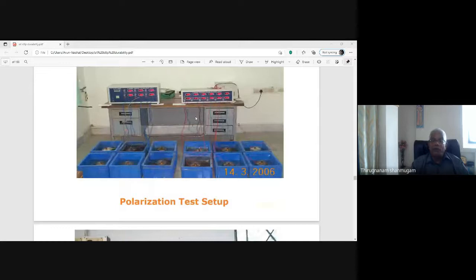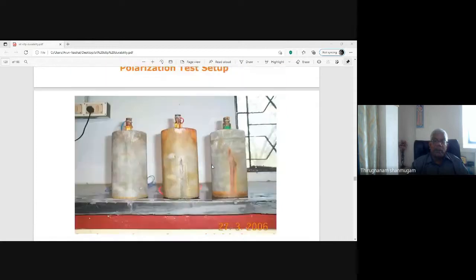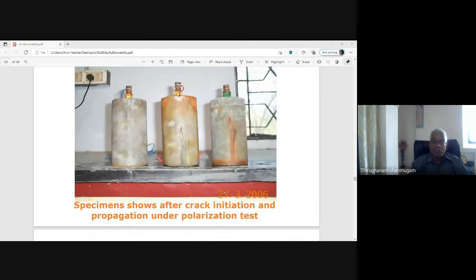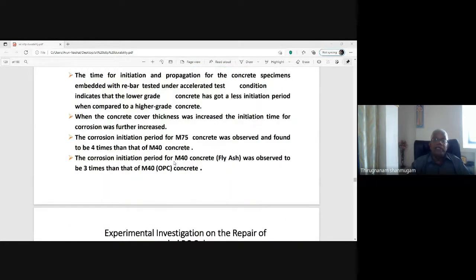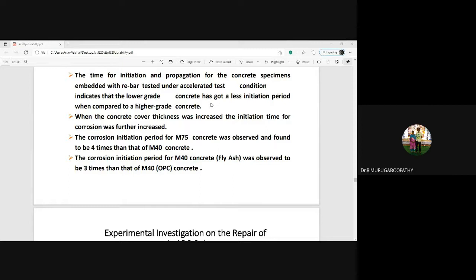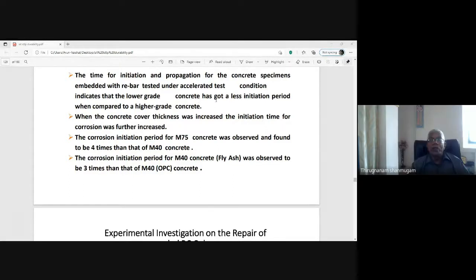This is the photograph of the test setup. It is also called a polarization test. This is a view of the concrete specimen after the corrosion. The specimen shows corrosion initiation and propagation under the polarization test. Steel reinforcement is highly corroded, with leaching of the rust solution. The time for initiation and propagation of corrosion in the concrete specimens embedded with rebar, tested under accelerated conditions, indicates that lower grade concrete has a lesser initiation period. When the concrete cover is increased, the initiation